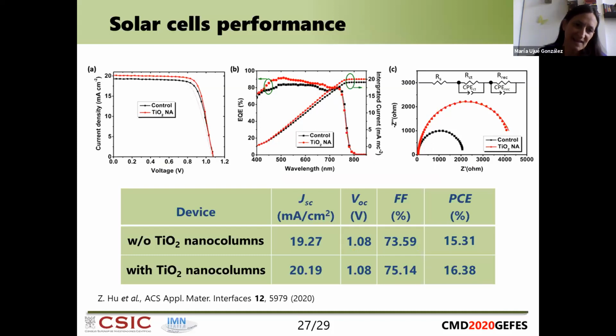I'm not going to go into too many details here because some of them I don't even understand properly, but the performance of the solar cells was measured with and without the nanocolumns. We saw that the photoconversion efficiency of our system was slightly better than 16% in the case of the sample containing nanocolumns, and 15% without the nanocolumns. So we were able to increase 1% with the nanocolumns. I know that 1% sounds very low, but when we are talking about solar cells, increases of 1% are very good. Still, this is far from the record for perovskite, but this was a very simple try, and we saw that the nanocolumns were increasing the performance of the system.